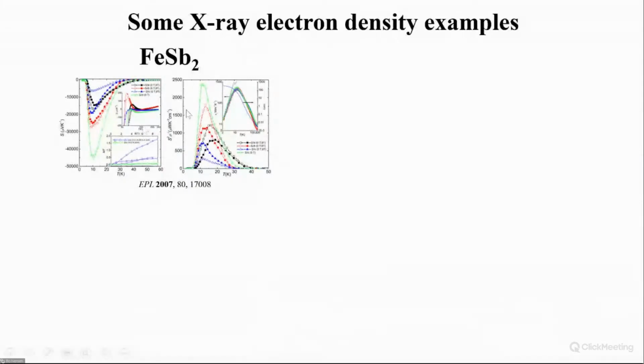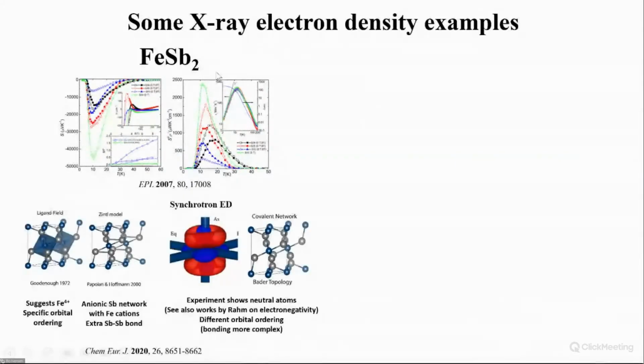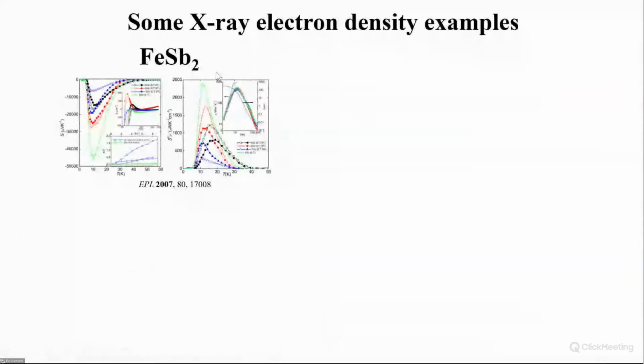So the first example here is something that we worked on a lot, I should say, 15 years ago. We discovered that iron antimonide has this gigantic thermal power, what is also called a Seebeck coefficient. Normally you would measure this in microvolts, but here it's actually in millivolts. So it's 3 orders of magnitude larger than normal, and we called it colossal Seebeck coefficient. And we spent 5 years at least on this, and many others did as well.